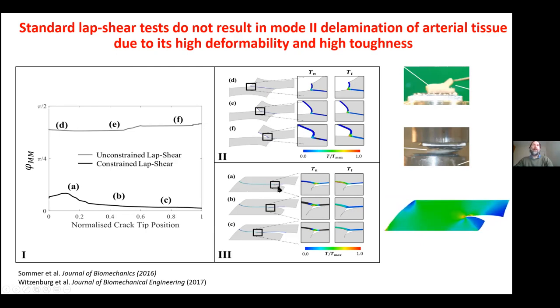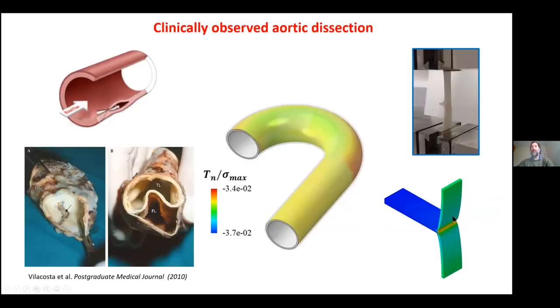And then when we zoom in, this is just at the start of the crack. When we zoom in on the crack tip, we actually see that we're getting a buckle at the crack tip. And in fact, this is not a shear test at all at the crack tip. If we look at the mode angle, how much of this is pulling apart like this versus shearing like this, it's nearly entirely pulling apart like this. Even though it's designed to be a shear test, because of the toughness of the material, it has to deform so much before we grow the crack that it ends up being essentially the same kind of test as this peel test, which, as I said, is not useful for this problem.